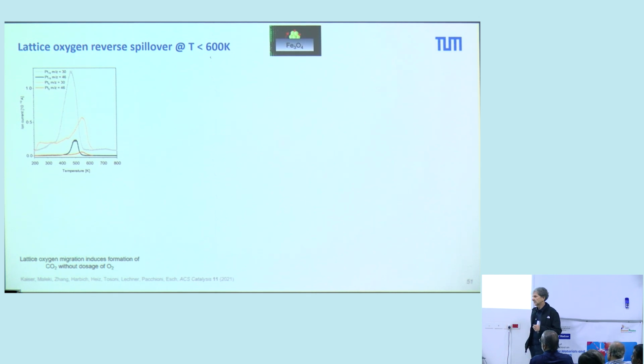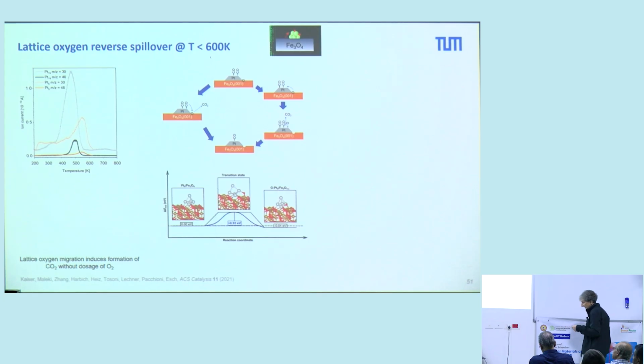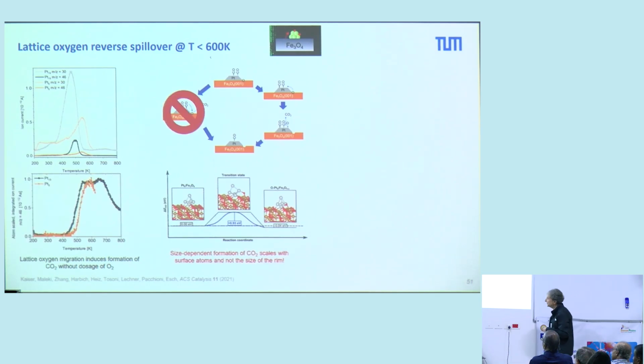Without putting oxygen into the chamber, we observe CO2. That means we produce CO2 on the surface. That means we have to have oxygen on the cluster. That means that for this to happen, we have to have a reverse spillover of surface oxygen onto the cluster. Of course, this reaction can now take place at the rim, at the interface of these clusters to the oxide material, or on the surface. But if you normalize the reactivity, you see that it scales with the number of surface atoms. So we are confident that the reaction takes place on the surface. That means we have indeed a reverse spillover onto the cluster.